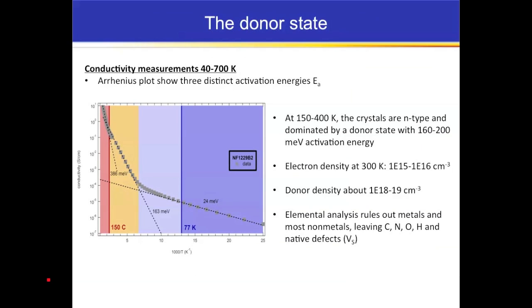The conductivity shows 3 different activation energies. Here's the intrinsic region, where we have an activation energy of about 400 millivolts. We can model this and determine what the band gap of pyrite is from this kind of data with a lot of other supporting information. And that's what leads us to believe that the band gap is about 1 electron volt at room temperature. The second activation energy here is this orange region, which is where the material is clearly N-type. And we have an activation energy of about